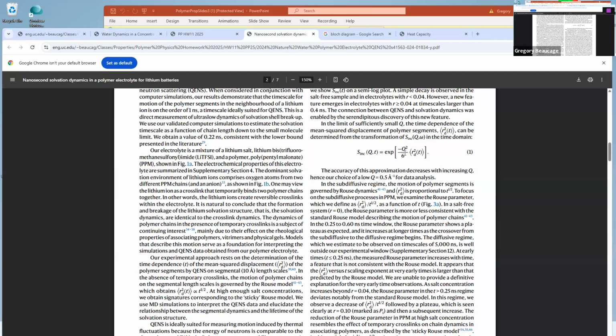But basically the way I see it, if you say you're at a fixed time, so time disappears, then this is just Guinier's law. It's like R squared Q squared over 3. There's something about this thing being 2 times dt or something. So somehow this ends up being Guinier's law. Guinier's law is for a cloud-like particle that doesn't have a surface. If you expand it, it doesn't have a surface term in the expansion. So it's just a Gaussian function with no end for the structure.